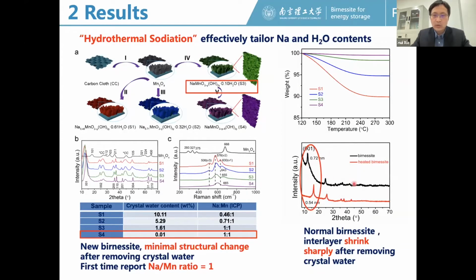Because for the traditional Birnessite structure, if we heat it and remove the crystal water, the interlayer distance will decrease from 0.7 nanometer to about 0.5 nanometer, which is a large loss of interlayer distance. But for the Birnessite structure we prepared in the present study, we find that this interlayer distance doesn't change much after we remove all the crystal water. It can still be retained at around 0.7 nanometer. So this phenomenon indicates that this Birnessite structure should be different from the traditional one.